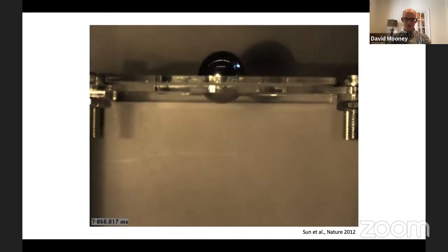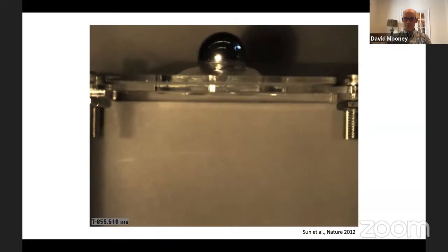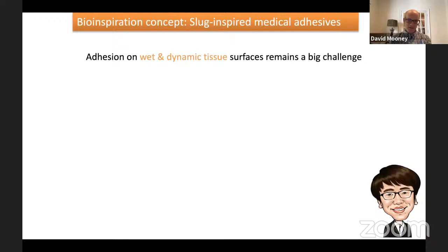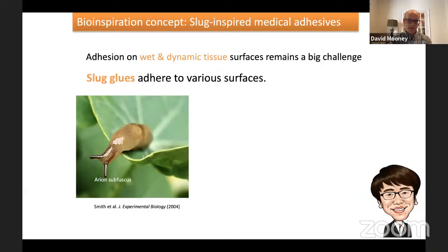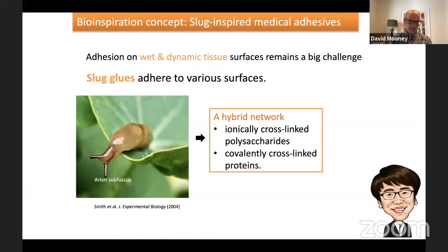So this was a nice demonstration of some fundamental material properties, but we didn't really know what to do with this. And then a few years later, Jianyu Li came into the laboratory, and he was very interested in medical adhesives. The challenge that he was interested in addressing is the fact that adhesion on wet and dynamic tissue surfaces is a big challenge, but that, unfortunately, describes most of the inside of our body. So he started looking around for where nature has already solved this general problem, and he came across this slug that you see the picture of here, and other scientists had already characterized that these slugs secrete a mucus that they normally use to move around, but when they're threatened, for example, by a predator, they change the composition of their mucus, and this allows them to adhere very strongly to whatever they're on and avoid predation.